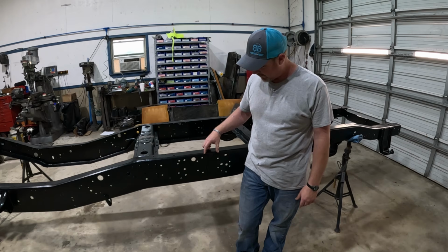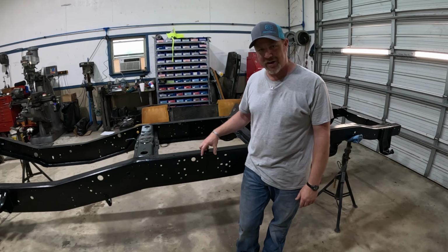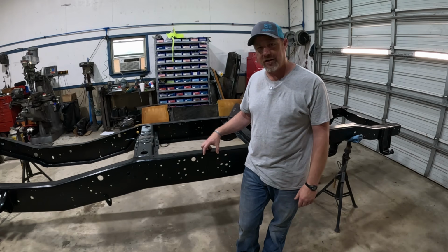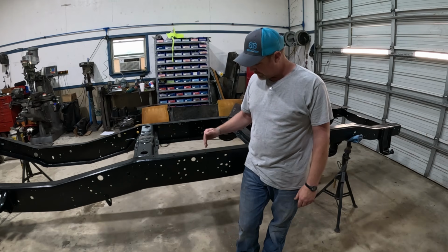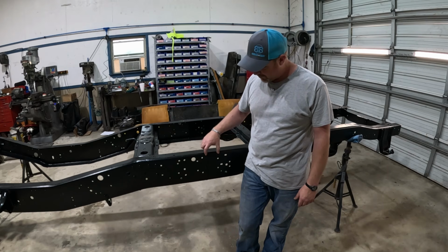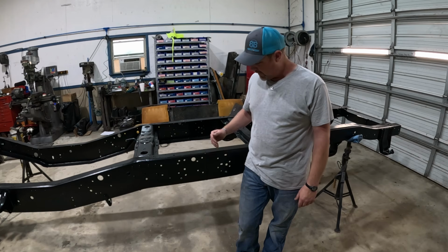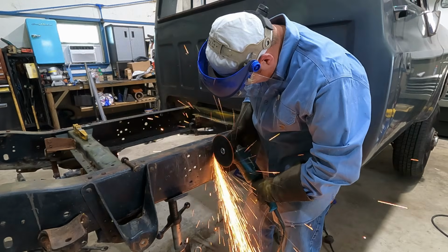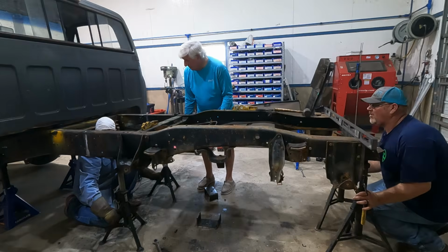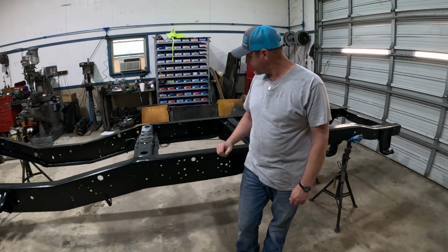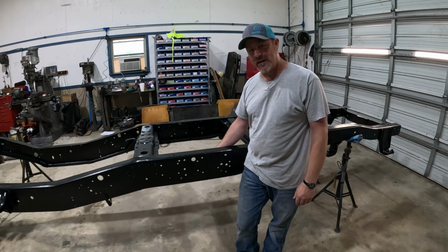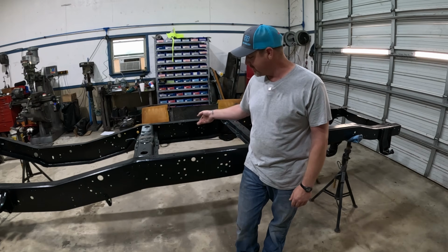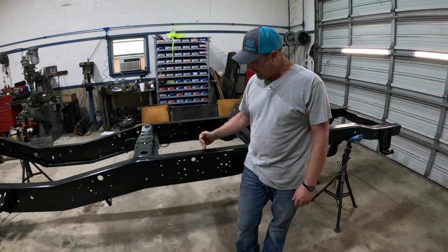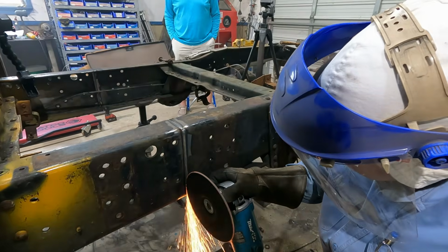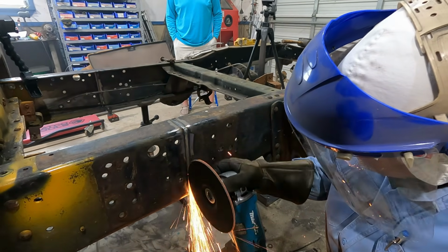We picked a spot where we either weren't going to cut out holes we needed or there weren't any holes at all. And we got good marks. We measured between them, made sure they were parallel. We got good cuts, and then we butted it right together. No gap at all. Then we welded it on the inside of the frame, all the way down on both sides. And then we came back from the outside and ground basically all the way through the frame material down to the weld metal on the inside.